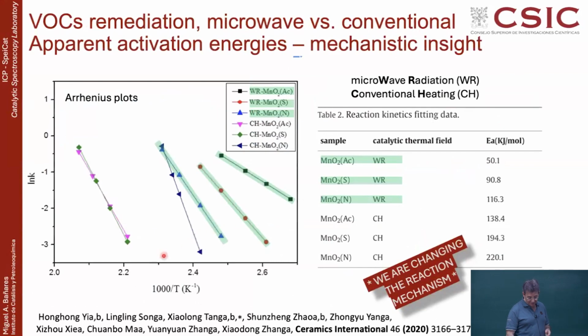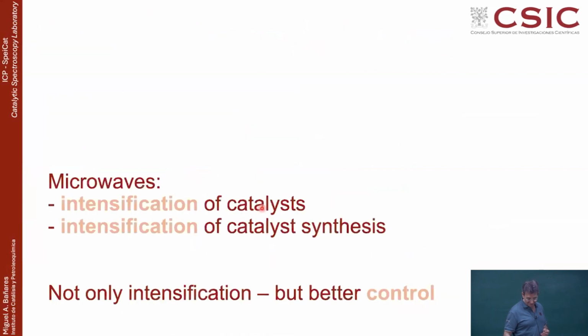And the most interesting thing when you are dealing with microwave is that if you compare a given reaction made by conventional heating or made by microwave heating, sometimes you find something interesting. The apparent activation energy changes. It's not only that a reaction happens at much lower temperature, which is one of the advantages of microwave, it's also that the apparent activation energy changes. So we are changing the reaction mechanism. This is quite recent because in photocatalysis, people already know you are changing the orbitals because of the interaction with light. You are changing the rules, but with microwaves, it would appear that there is something else, not only a very efficient heating effect, but something else. And this change in apparent activation energy is actually telling you that there is something else. So that's part of it.